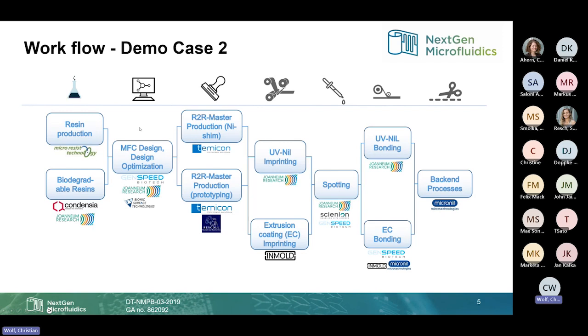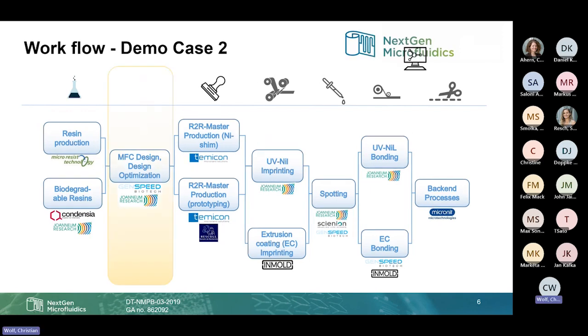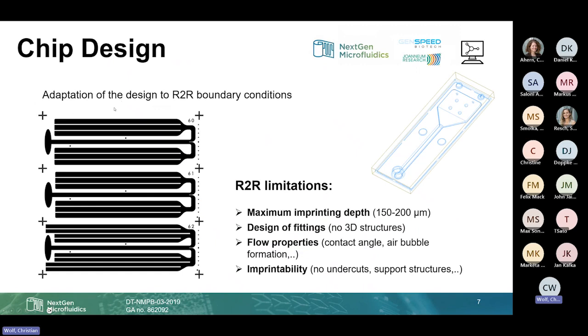For example, let's start with this design step here. As I already said, you have to adapt your design to the roll-to-roll limitations and boundary conditions. When you look here, that's the design of the commercial injection molded ChipShop chip, what it looks like at the moment. And here on the left-hand side, you can see the final design of our roll-to-roll imprinted chips. And you can see there's quite a big difference. And that's mainly because of two limitations of the roll-to-roll imprinting process. One of them is that we are limited concerning the imprinting depth. That's typically limited to 200 micrometers, something like that.